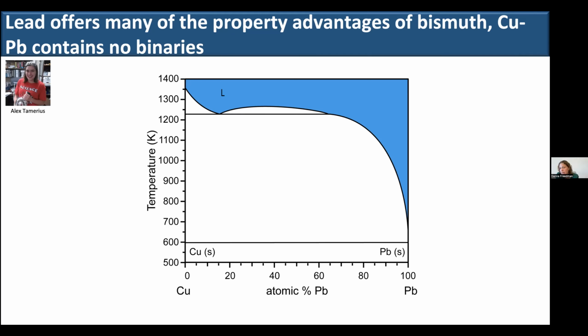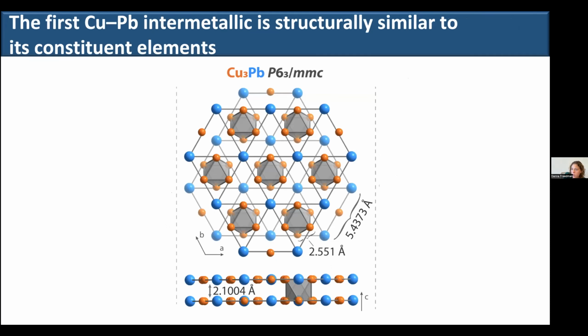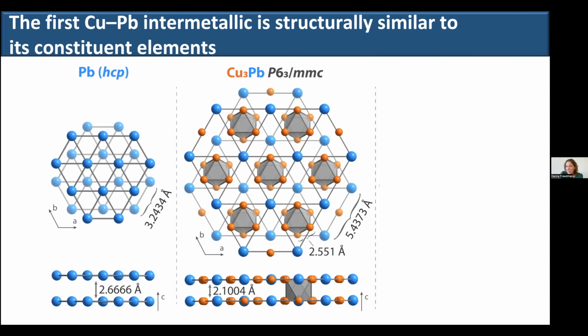At ambient, lead and copper have almost comparable electronegativities. So what happens when we get into this space? Again, we are looking for materials that have interesting band structures that are influenced by the spin-orbit coupling, and one way to do that is to tune the electronegativity to create those structures. My student Alex synthesized the first copper-lead binary compound, motivated by all of those factors. What we find kind of cool is that if you look at the HCP structure of lead, which is the structure at the pressures we're synthesizing this material.